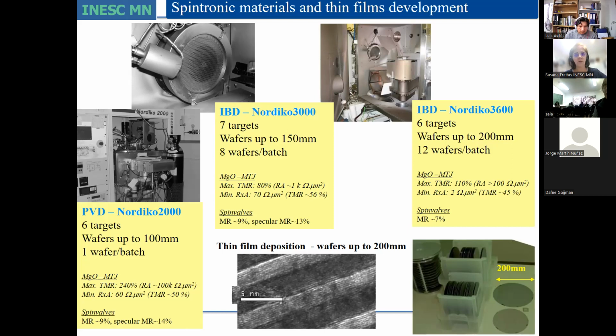Since I was a PhD student, I was always used to working with companies. From time to time, companies approach INESC, and they ask us, for example in the case of materials, to evaluate, instead of manganese iridium, manganese nickel, a different material. It was easier for us to replace one of our targets. So they send us a target, they pay for the target, and we install it in our machine and make a series of samples with their material. If the results are good enough, they will consider buying the target for their production line. This is an example of collaboration because we were fast in assessing the quality of the materials.